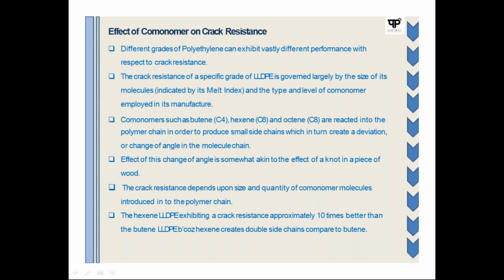There are co-monomers being used in LLDPE, or a combination of co-monomers is used in LLDPE material, that is C4, C6 and C8. Here hexene exhibits crack resistance 10 times better than butene material. The combination of these co-monomers plays a vital role in increasing the crack resistance, to increase the ESCR. So the permutation and combination can be done by using these monomers to get the right quality of the material.